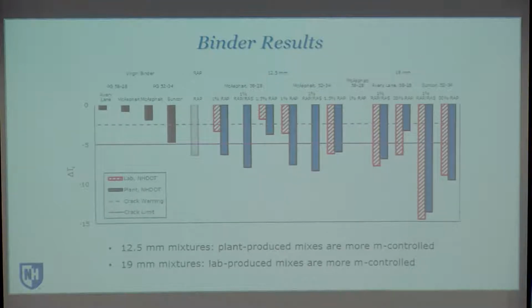Okay, and this is where it really shows up. So this is the delta TC value. You can see for the Avery Lane and the 2 McAsphalt virgin binders, okay, those are pretty good in terms of starting off with for the tank binders. Okay, the 1 McAsphalt, the 52-34, that's a little bit closer to our crack warning line. Okay, but our Avery Lane and McAsphalt, those are actually fairly good.